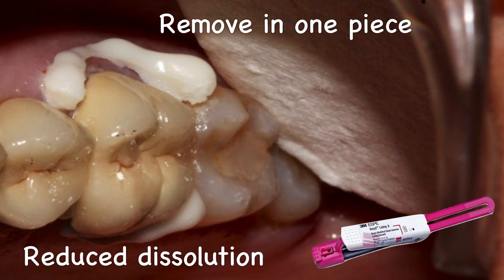More importantly, once the entire procedure is done, I use a glycerin jelly which is placed on the margin of the crown, and I tack cure, or rather completely cure through that. What is the advantage of doing that? Any oxygen inhibited layer that is present at the margin will also get polymerized, which means now the micro leakage substantially decreases, which means I will not have issues of secondary caries creeping in because my GIC cement has dissolved. So RMGIC has become a big favorite for me if I have to cement metal crowns, porcelain fused to metal crowns, or even zirconia based restorations.